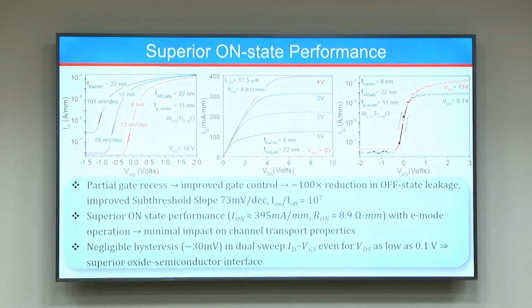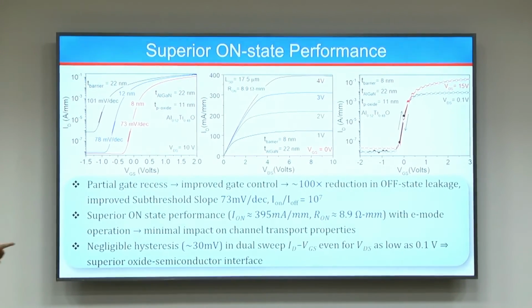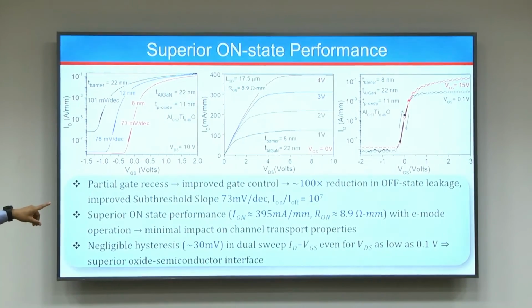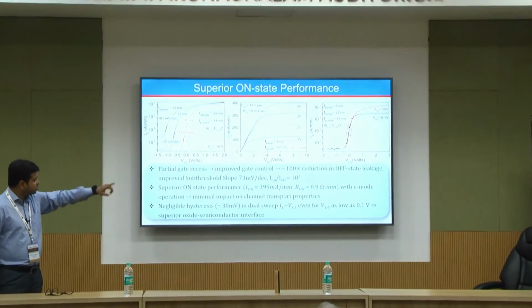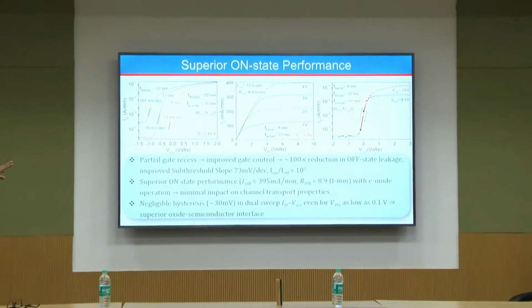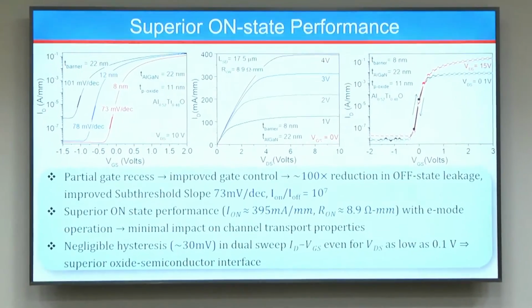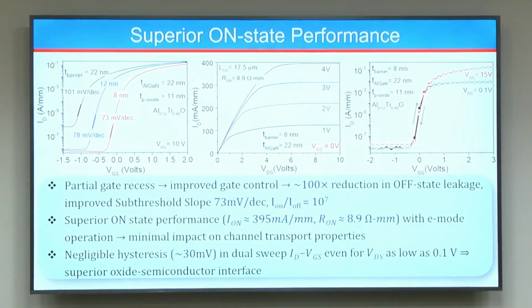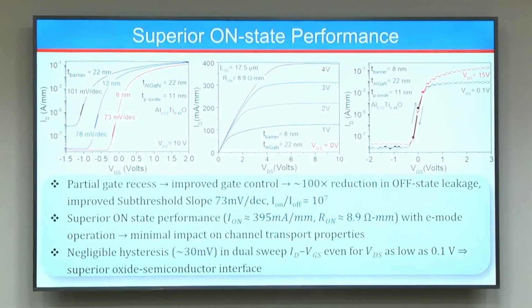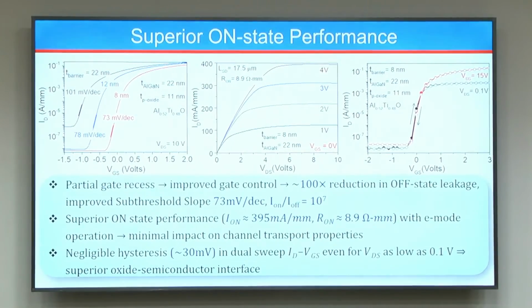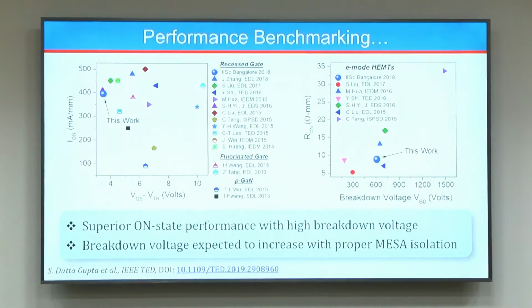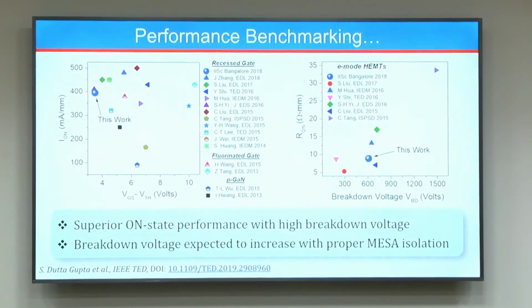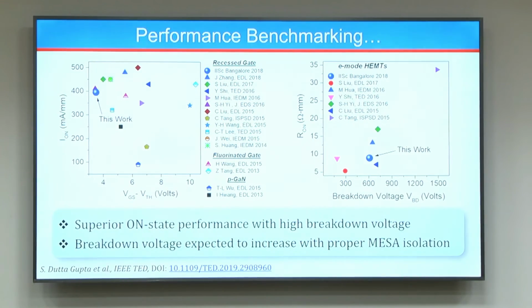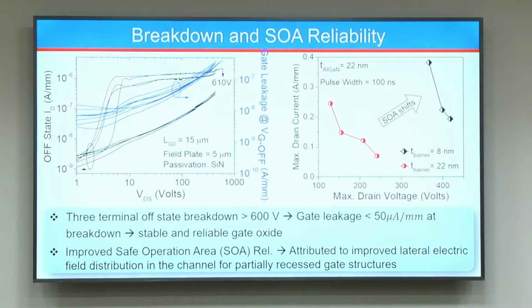Now if you see the drive currents, there is no self-heating issue, there is no dynamic R-on issue, there is no trapping issue. As you see in the hysteresis plot there is no trapping issue in the gate dielectric, right? And for 600 volt breakdown voltage, we are getting very low on resistance, 8.9 ohm millimeter for a 600 volt breakdown voltage device. So we also compared with the best numbers reported elsewhere.